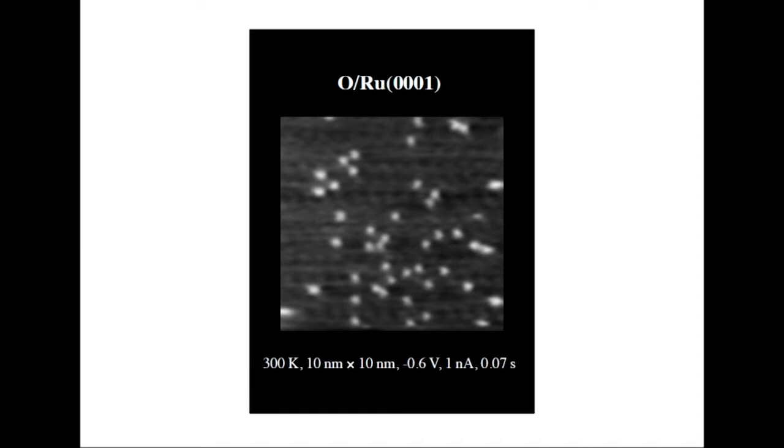If they come close together, they stick a little bit longer together because there's a weak attractive force between neighboring oxygen atoms. And this has the consequence that at higher coverage, the distribution of the atoms across the surface is no longer random and uniform, but we have a separation into two phases. This is the emergence of a new phenomenon. We now have a diluted phase, a quasi two-dimensional gas phase, and a condensed phase, a two-dimensional crystal phase.